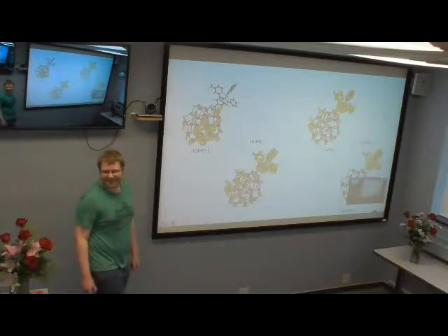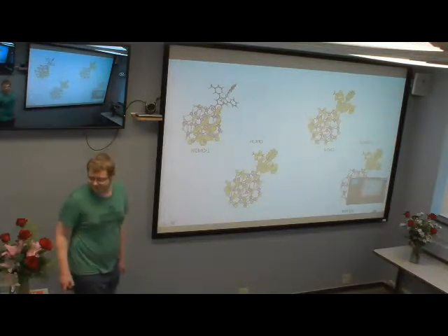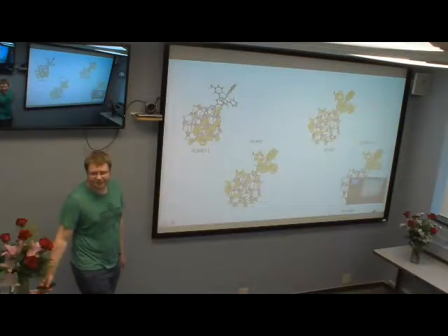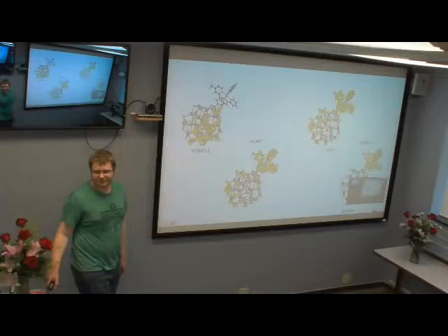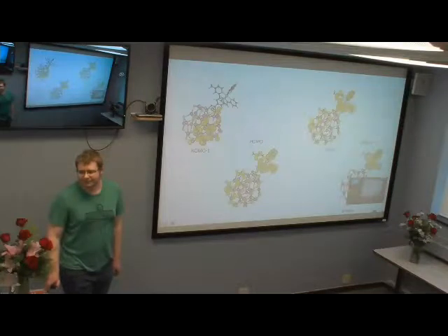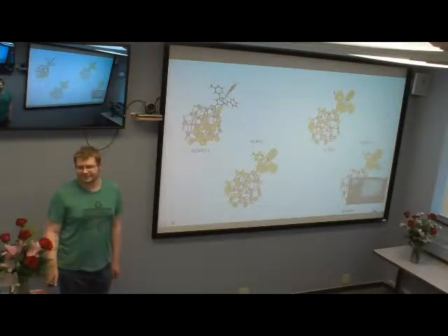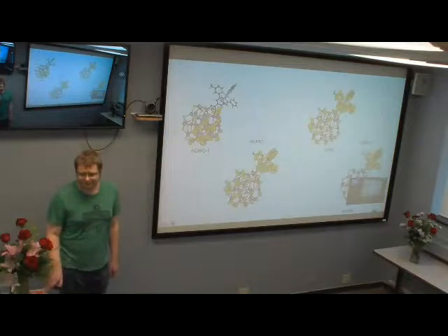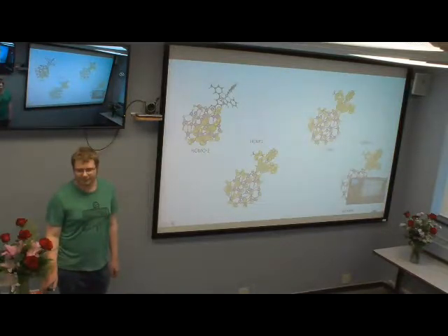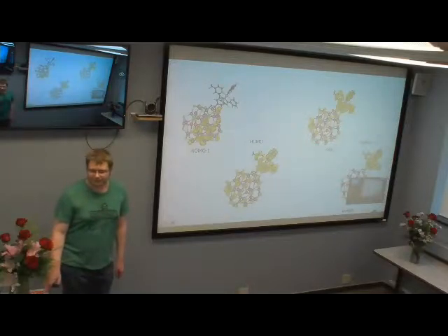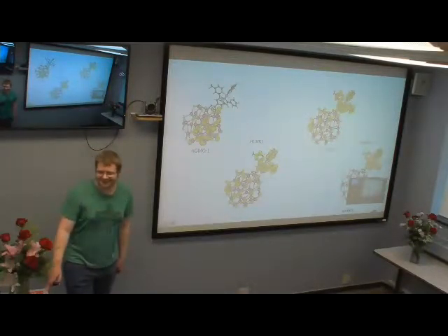The regular size of quantum dots people are comfortable working with is from 2 nanometers up to 4, in this range. This is the typical range of quantum dots where they're really interested in quantum effects and confinement effects, right? So our system's a little bit below this, but experimentally they call it magic size quantum dots. People have shown you can create such quantum dots. It just requires a more sophisticated approach, and it's much easier to synthesize and work with a little bit larger size, right? But it's a few nanometer size system, which is a reasonable size, and again reasonable in terms of calculations because you're not spending a lot of time.